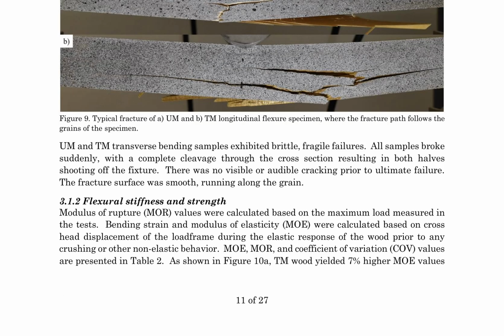The modulus of rupture, MOR, and modulus of elasticity, MOE, values were calculated from the maximum load and bending strain, respectively. TM wood exhibited 7% higher MOE values and 5% higher MOR values compared to unmodified wood. However, these values varied from those reported in the Wood Handbook for Western Hemlock, potentially due to differences in grain structures, density, and forest characteristics.